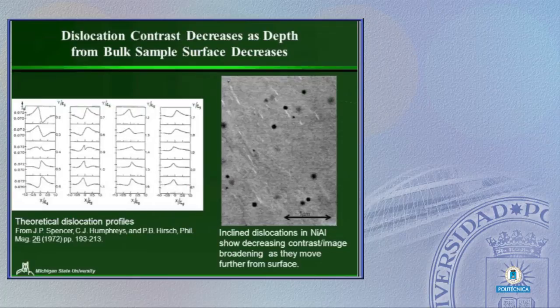Now this is kind of a noisy image here, but I want to show you that people look at these things and say, yeah, well, the dislocations look a little bit different than they do in TEM. Well, you might expect them to, because we have a bulk sample, and we're only really looking at the dislocations that are close to the surface. In fact, theoretical work was done in Peter Hirsch's group many, many years ago on this, and shows that if we take the trace across a dislocation line, as you go deeper into the sample, that intensity, peak to background, is going to decrease. As a result, we can imagine that the dislocations are going to be sharp where they exit the surface, and as they go deeper into the sample, they're going to become noisier and eventually disappear. At first people say, well, that's sort of inconvenient, but the reality is that's a really good thing.